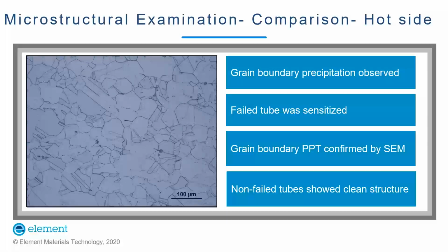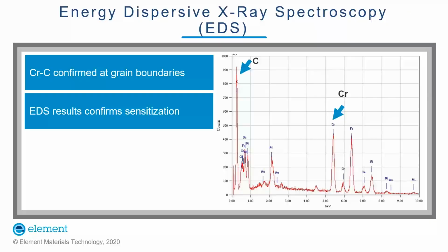The study also explained why other tubes didn't fail and only one tube failed and cracked during operation. As mentioned before, the EDS was performed on the failed tube during the SEM study, and what we see is the presence of chromium carbide at the grain boundary, which confirms very clearly that the failed tube was sensitized.